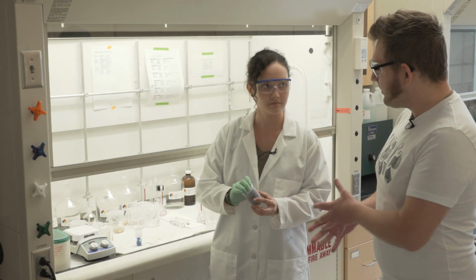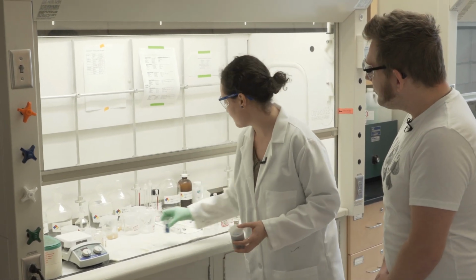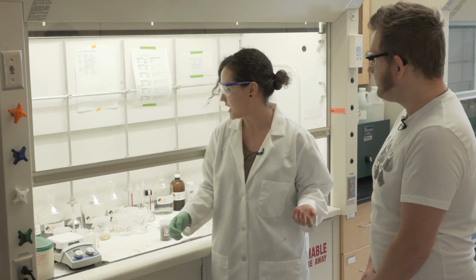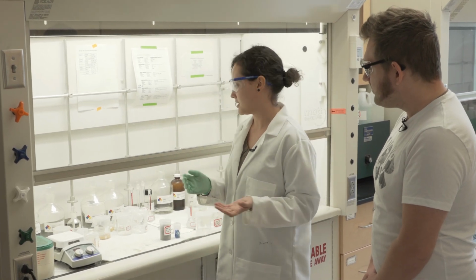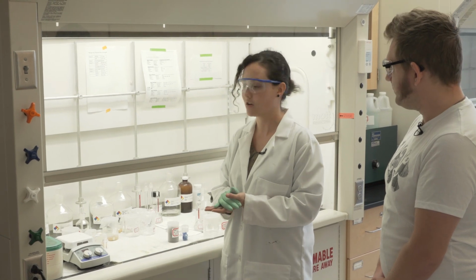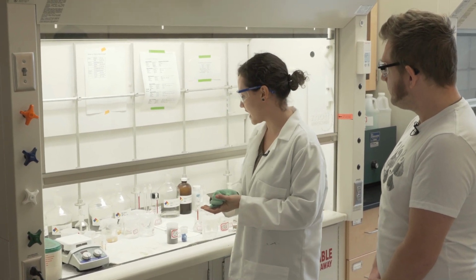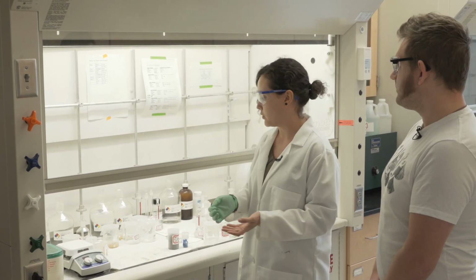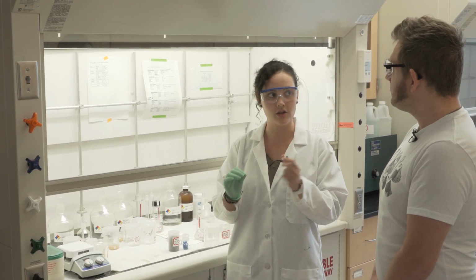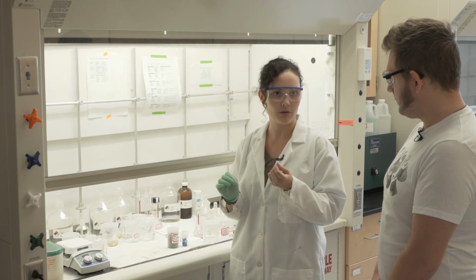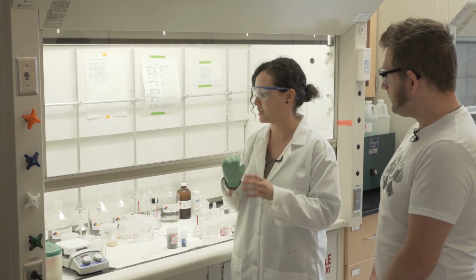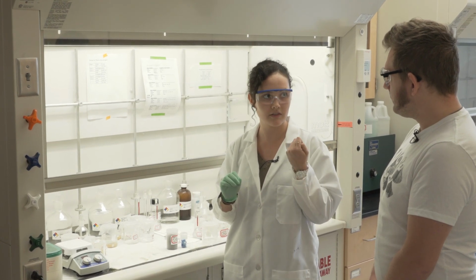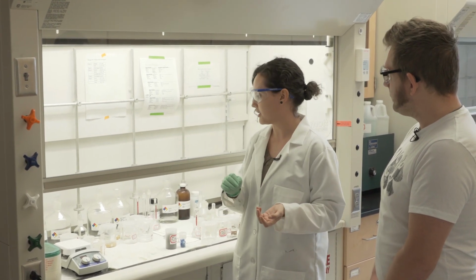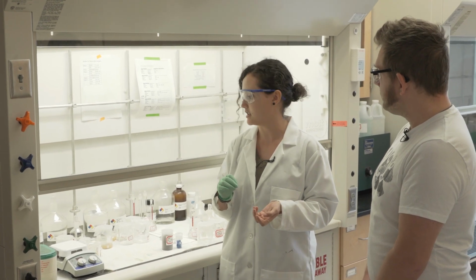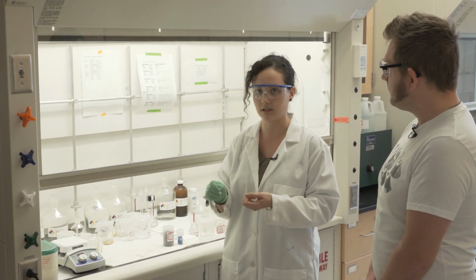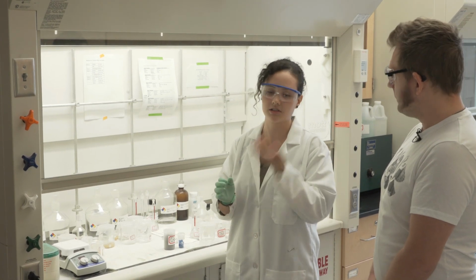So how do you make these kinds of materials? How are they different than silica aerogels? So the method that we use is called the sol gel method. There are several ways to make these aerogels. One is called the precursor method, and the other one is called the impregnation method. What I've been using recently is the impregnation method, where you first start with a regular alumina gel, and then you impregnate that gel with a copper or any other metal solution. You let that sit, you let that gel, and then eventually you extract the solvent, and you leave out the aerogel. The other method that I've been doing recently with ceria is the precursor method, which is where you gel both the cerium and the alumina together, and then you extract the solvent after.